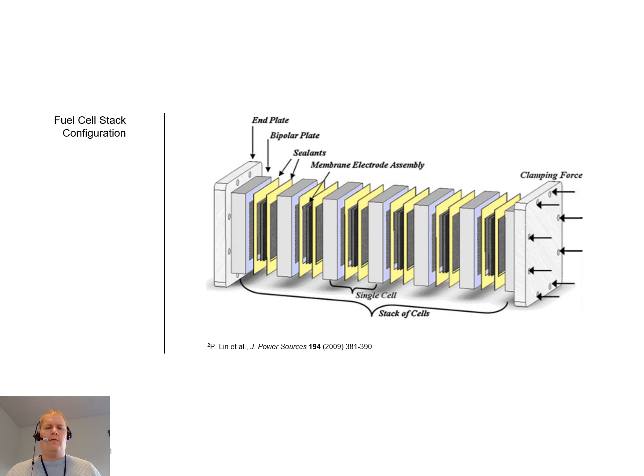To achieve high power, you have to stack the single cells on top of each other, creating a so-called fuel cell stack. The fuel cell stack comprises end plates at the very ends, and then you have the single cell that I just described on the previous slide. So each single cell has two bipolar plates on the anode and the cathode side. Then you have sealants, and then you have the so-called membrane electrode assembly in the middle, which comprises the membrane and then two catalyst layers and two GDL layers.